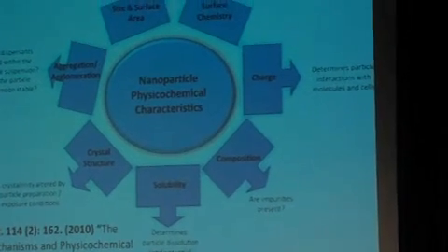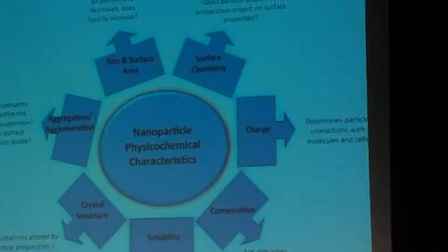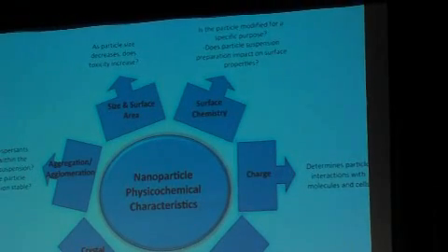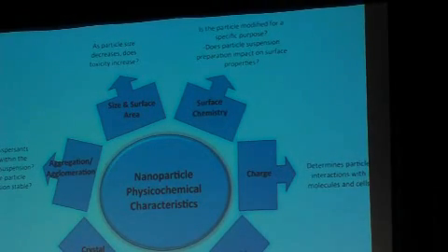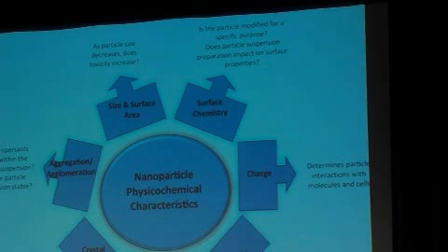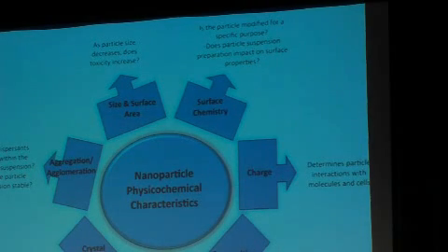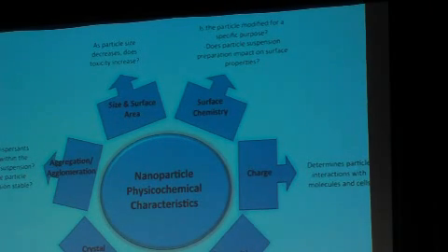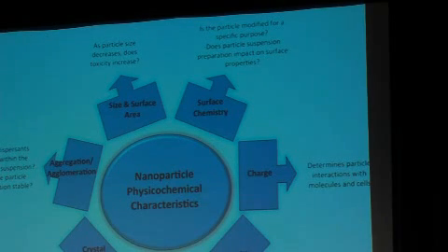The charge is determined mostly by the surface chemistry, which is going to have a big impact on the function of the nanoparticle. If you have nanoparticles for different purposes, you're going to have different surface chemistries, and that surface chemistry may make the same nanoparticle present different risks. For example, one may be a flight risk with rapid transport in an environmental context, and another may be relatively stay-at-home because it adsorbs strongly onto soil, and so it's not so much of a problem.